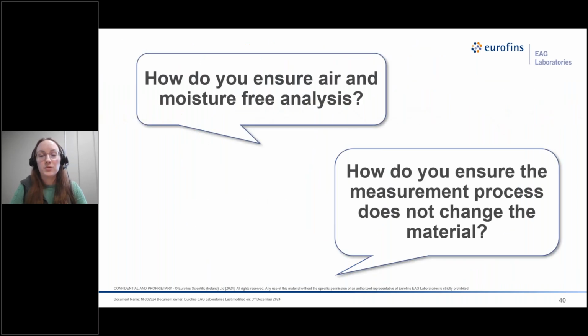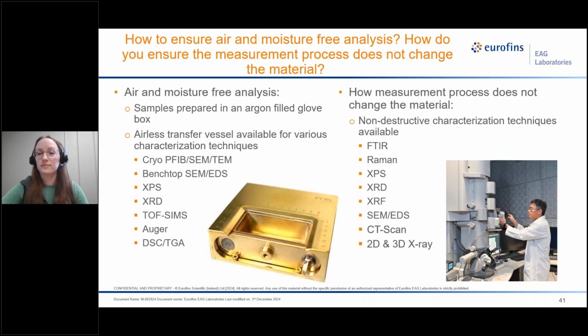And now when we're dealing with all these different types of characterization techniques, we have clients ask how we ensure this air and moisture-free analysis and how to ensure that the measurement process does not change the material. So as mentioned, we have a dry room and an argon-filled glove box, and we can ensure that air and moisture-free environment by doing our sample preps in the glove box. And then we have various characterization techniques that allow for airless transfer vessels, and this would include cryo-PFIB, benchtop SEM, our XPS, XRD, TOF SIMS, Auger, and DSC and TGA.